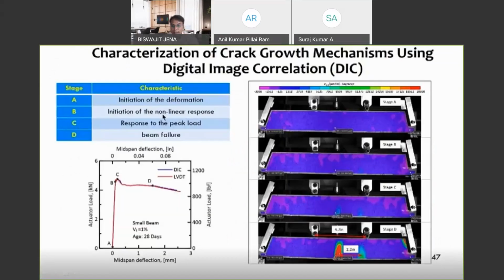So next, to give you a few important points in the load deformation plot, if you see the top picture, stage A corresponds to just the static loading pattern. You have almost no strain set up in the material. So whatever pink strains you see at the edges are from the compression of the loading support. It is not really the effect of loads, but you just start to see some patterns of strain emerge. Again, at stage B, it is pretty close to the peak load, and you will have some tensile stresses that you see at the bottom and more compression in the top.